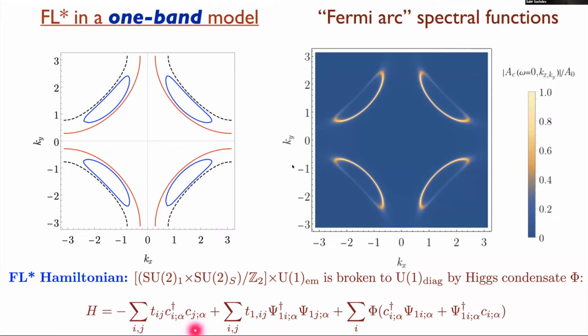And so you have the physical electron, you have the first layer, and then you have the hybridization between them. And this actually completely breaks these SU2 gauge groups. The only thing that's left over is the SU2 on the second layer, on the bottom layer, which I'll say a little bit about maybe. Okay, so here's what we're going to use to fit the data. The Tij we know. The T1 ij are our free parameters. And the phi determines the pseudogap, which we also know.